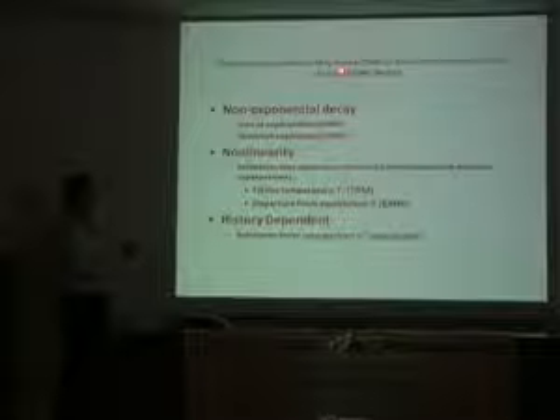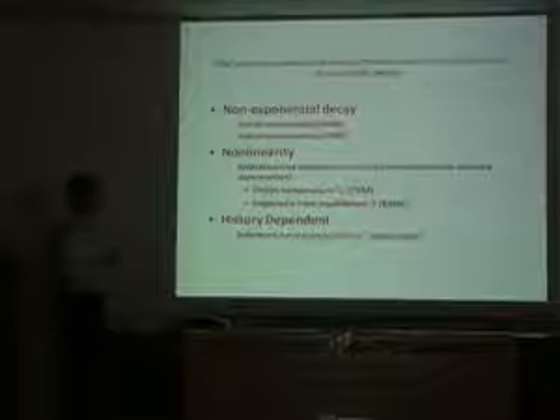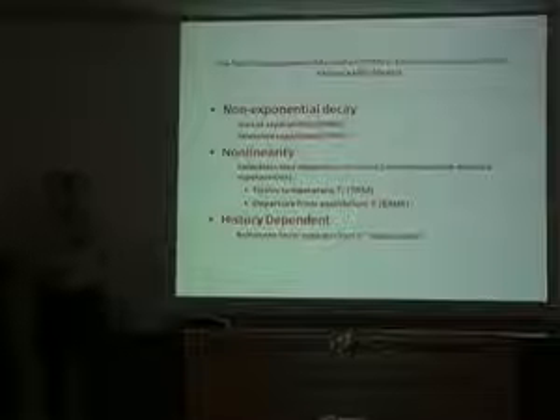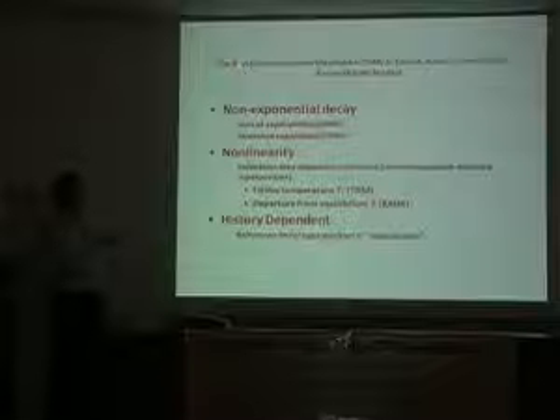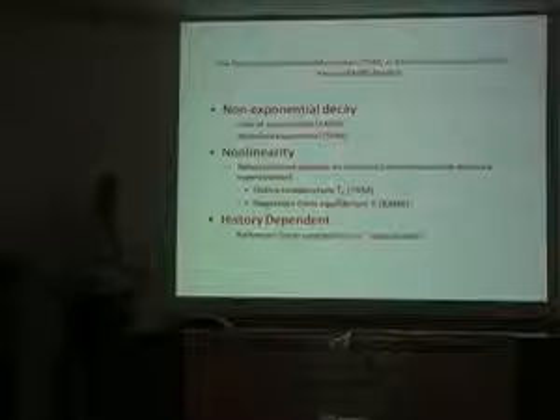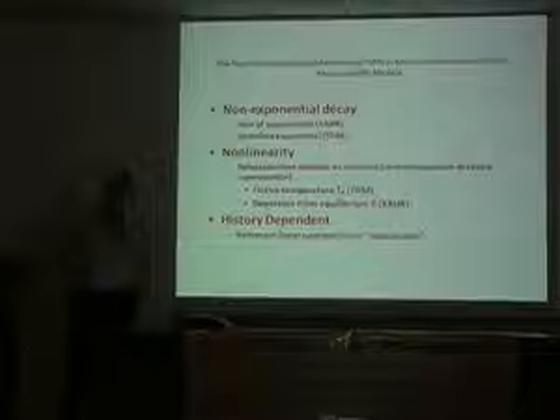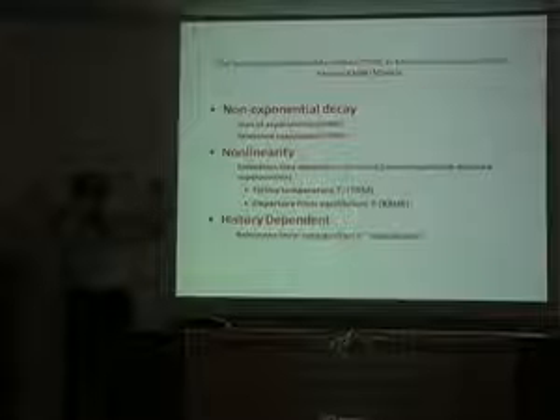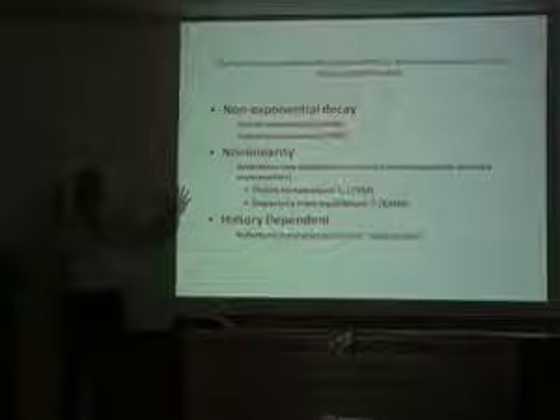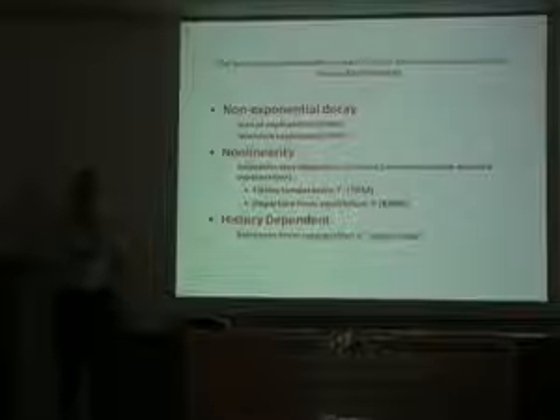And so what the Tool-Narayanaswamy, Moynihan, or Kovacs, Aklonis, Hutchinson, and Ramos models do, and maybe I should tell you who these people are. Okay, Tool was actually in the glass division at the National Bureau of Standards back in the 30s and 40s, and did a lot of work, and he was the first one to see the asymmetry of approach, actually. Narayanaswamy was a mechanical engineer at Ford Motor Company. Something practical. So Narayanaswamy had a problem with Ford in the late 60s. They were trying to make windshields that are more curved, and they were breaking because the residual stresses in them were wrong. And he developed this model partially to help overcome the problem of residual stresses and cracking windshields.